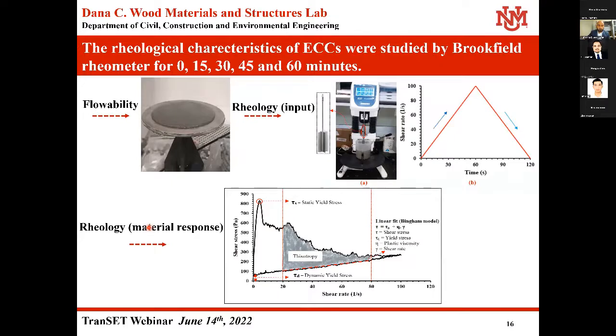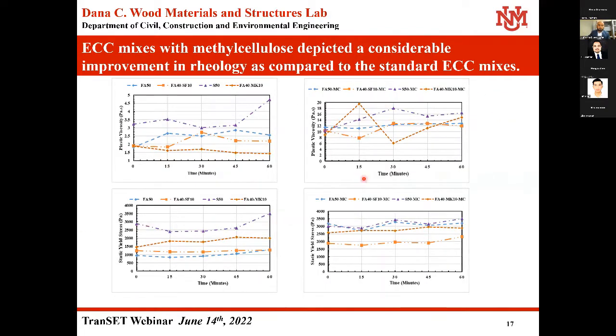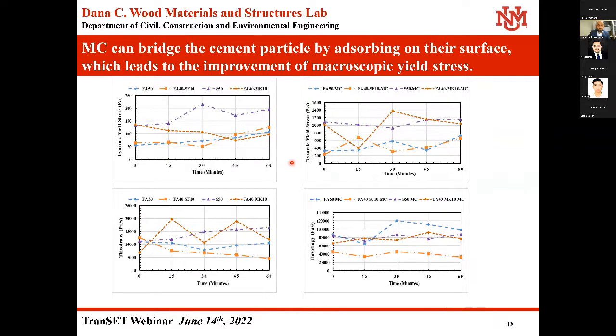For the fresh properties and printability, the flowability and rheology were measured using a Brookfield rheometer. With the inclusion of methyl cellulose in the mix, the rheology was considerably improved. Rheology parameters such as plastic viscosity, static yield stress, dynamic yield stress, and thixotropy were considerably improved because of the inclusion of methyl cellulose, as MC has the potential to adsorb on the cement particles and bridge them, leading to an improvement of macroscopic yield stress. Ultimately, this phenomenon improves the thixotropy of the mix.